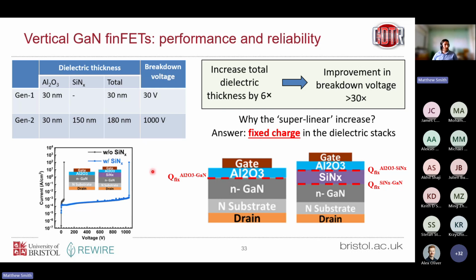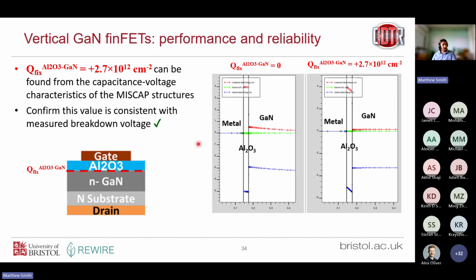So what we did was model fixed charge purely at interfaces here. That's not necessarily the case, but if we localize fixed charge here, it gives us a chance to model it and get some numbers out. So first of all, we looked at this generation 1 device. We got this MISCAP test structure.